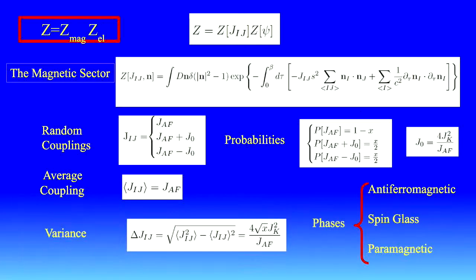So, the partition function has a magnetic component and an electric component. The magnetic component is a Heisenberg-like interaction between the antiferromagnetic components of the localized spin, with a coupling which has three possible values, with these probabilities. And this gives this average and variance. So this is the magnetic part of that.